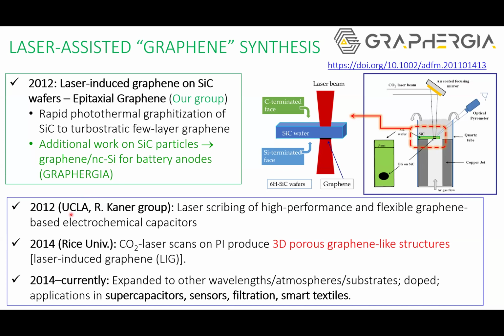At about 2012, from UCLA, the Kaner group was the first one probably that used lasers to reduce GO and prepare micro flexible interdigitated supercapacitors. There is a famous Science paper for this work. And then in 2014, at Rice University, the Tour team used the CO2 laser to decompose the polyimide, actually, and produce 3D porous graphene. But as I mentioned, this work was already done and known for almost 30 years before the Rice group did the work. But actually, the LIG term was coined at that time, and the laser used for graphene production became more popular after the publication of the Rice group paper.